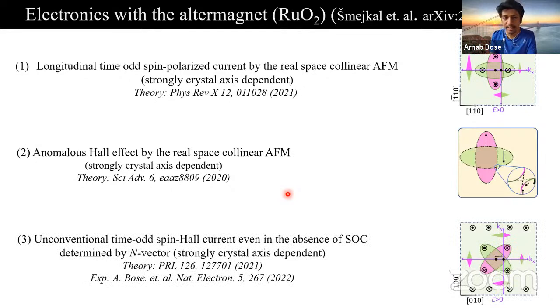The third possibility is that even if there is zero spin orbit coupling, this material can still produce transverse pure spin current, which is fundamentally different from the spin Hall effect, because for the spin Hall effect, the requirement is spin orbit coupling. Unlike this case, here the requirement is the spin split bands. And another difference is the generated spins are polarized along the direction of the Néel vector. So this is a theory prediction, and this is our experimental demonstration.